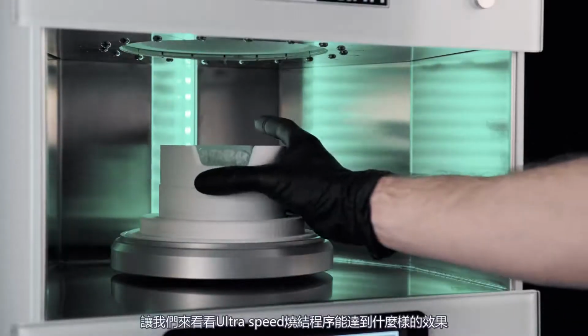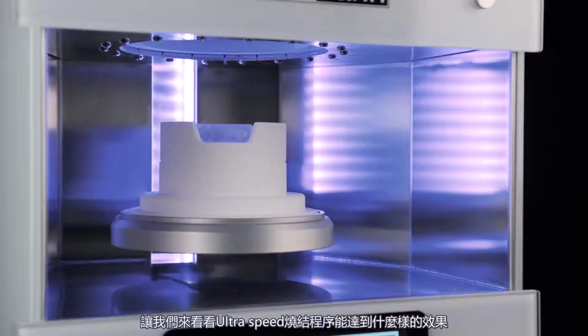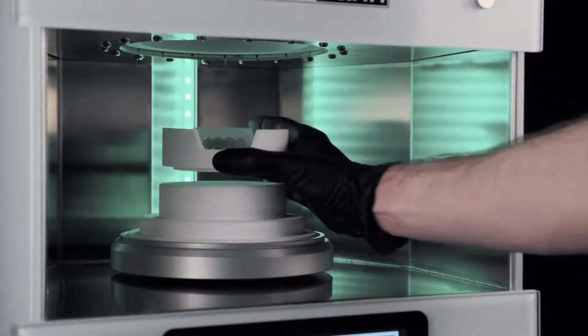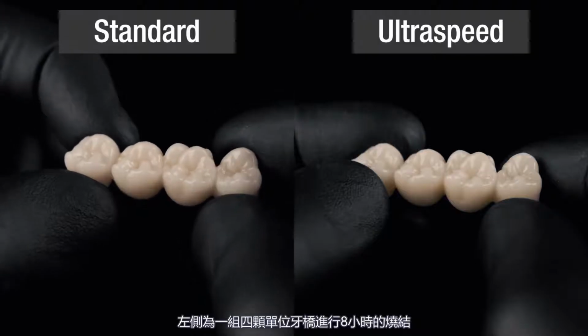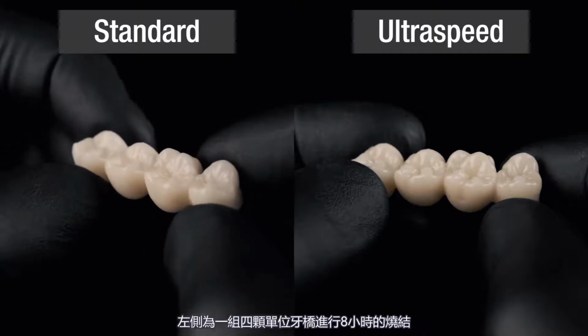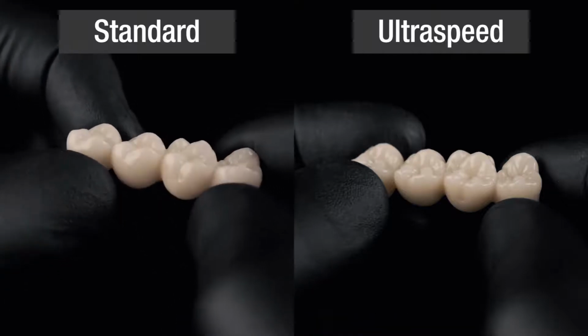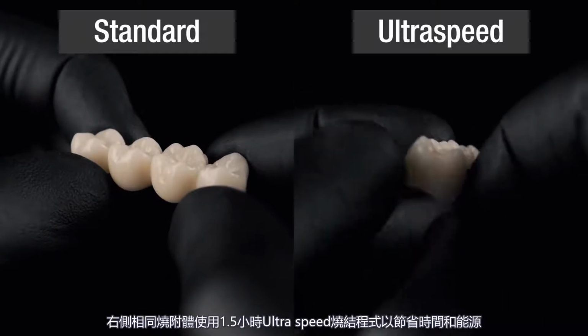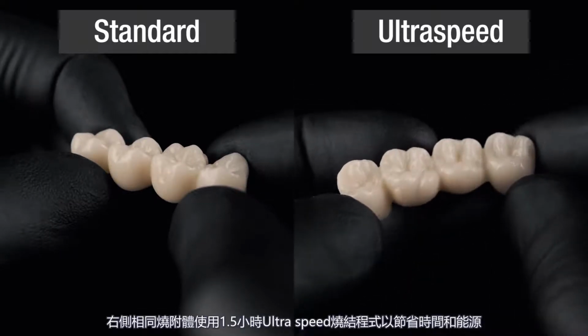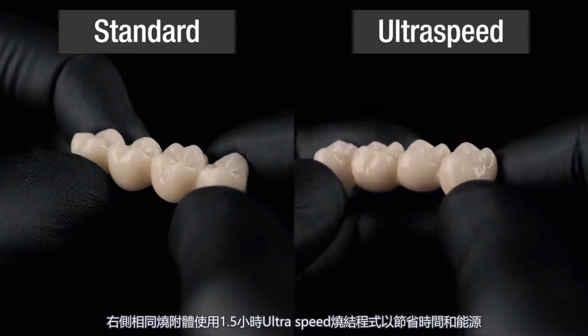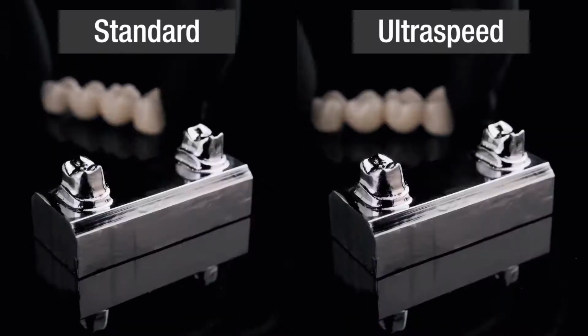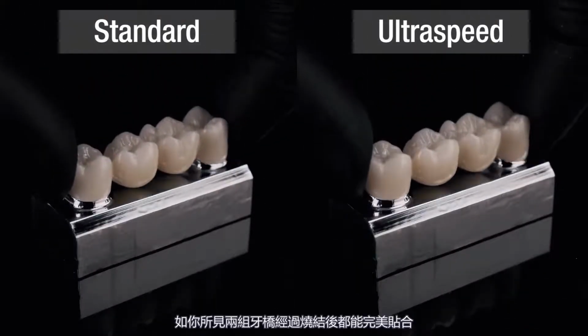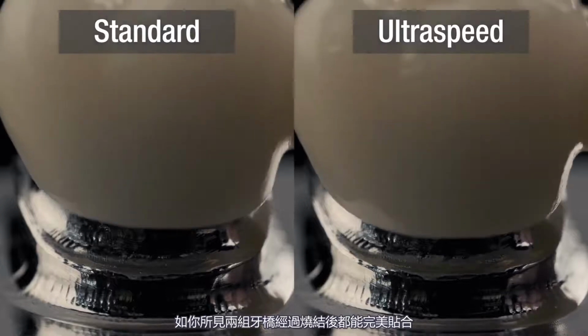Let's take a closer look at the precision of the Ultraspeed programs. On the left, we sintered a 4-unit bridge with the standard program in about 8 hours. On the right, we sintered the same structure in just 1.5 hours with the Ultraspeed program, saving time and energy. As you can see, both bridges show an extremely accurate fit adjustment after sintering.